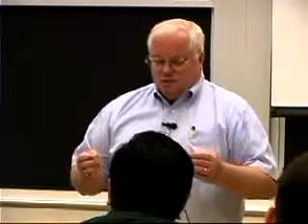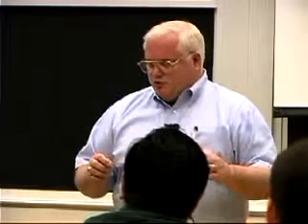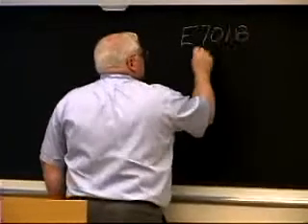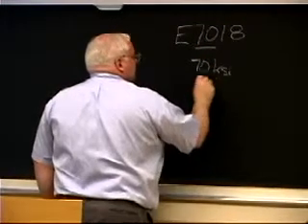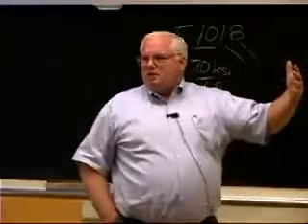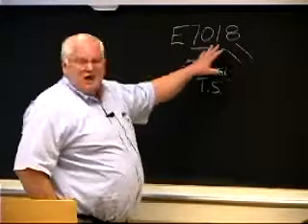This is a 7018 welding electrode, and now instead of just sticking it in the mud, this is a very specially formulated material made out of all kinds of fancy things like limestone, silica, iron oxide, manganese powder. Very proprietary compositions. Every company has their own special compositions. The 7018 number on here is a shorthand for E7018, which is the American Welding Society designation. The 70 means it has 70 KSI tensile strength, and the 18 tells you other things about the type of flux coating and the type of position that you can weld in: overhead, horizontal, flat. Not every electrode works in every position.